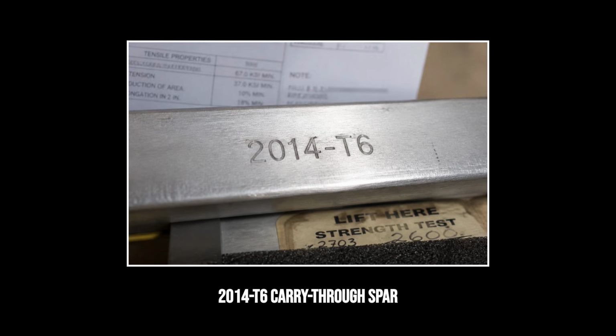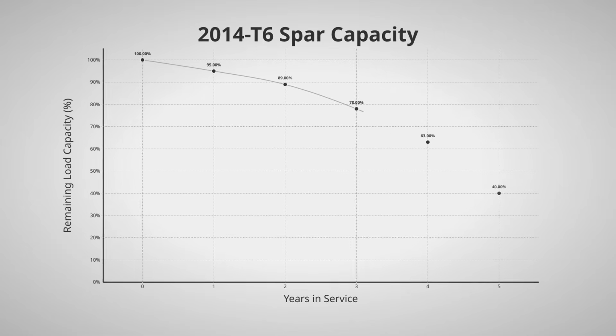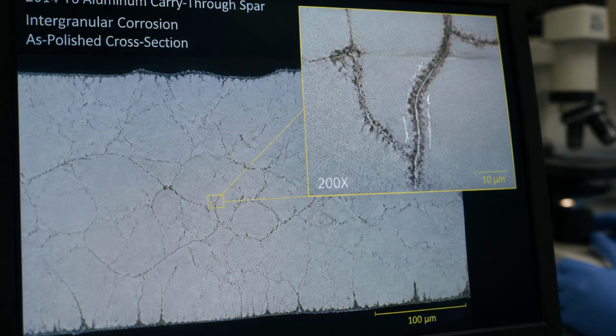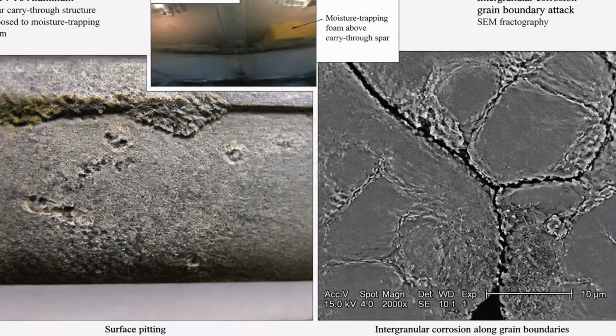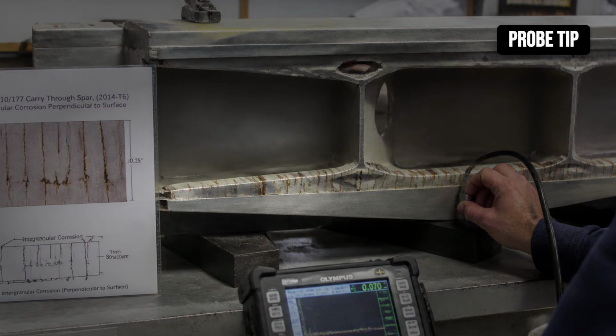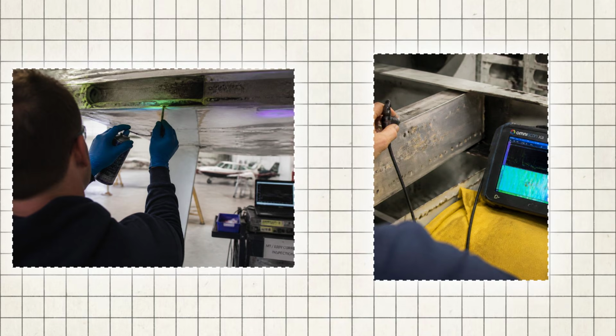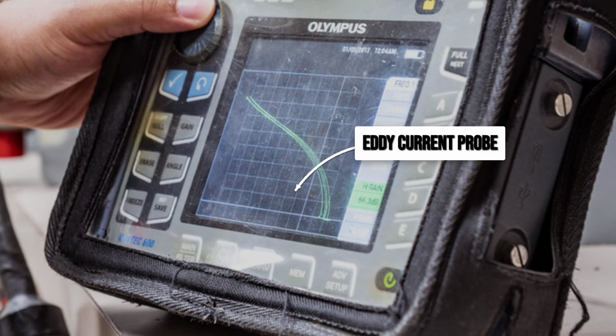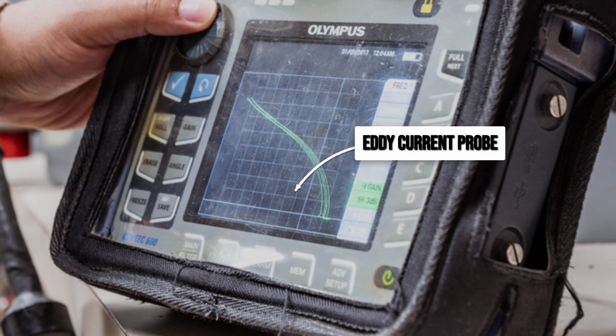The 2014 T6 aluminum in that spar is a high-strength alloy and one of the most corrosion-susceptible in the 2000 series family. Its vulnerability is intergranular corrosion, an attack that works along the grain boundaries of the metal rather than across the exposed surface. A spar that looks clean on a visual inspection can be corroding internally, the attack working inward along pathways that run perpendicular to the surface. The eye cannot see this. The dye penetrant test a shop runs on a suspected crack cannot reliably find it in this orientation. Only eddy current testing reads the subsurface condition accurately.